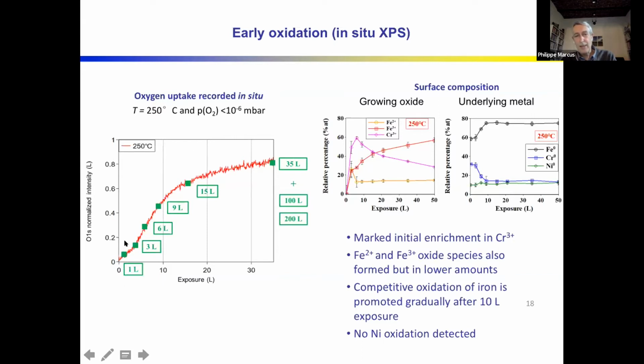So looking at this scale of time at low pressure is equivalent to looking at just the first few nanoseconds of oxidation at ambient pressure. So that provides a unique way to look at the nucleation and growth of oxides, in that case on stainless steels. We can see that we have first a striking enrichment of chromium at the surface, then it goes down because iron starts to be oxidized. So this is the XPS.